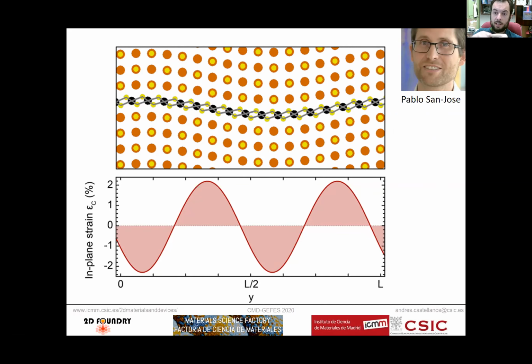Basically, the pseudo-tetragonal and the hexagonal lattices have lattice parameters that are incommensurate, so they cannot fit to each other to make a nice moire pattern. But just by deforming the layers slightly in plane, they can become commensurate, and that does reduce their energy, becoming more favorable. Therefore, what this model says is that the most stable solution for the lattice is to have this spatially varying strain profile in plane. So the atoms get expanded, compressed, expanded, compressed, in order to accommodate each other's lattices and become commensurate. So we start from a system where, when we stack the layers, they should be isotropic. And once they start to interact, the atoms start to move around a little bit in order to accommodate the two lattices. And they do that by breaking the symmetry of the system.